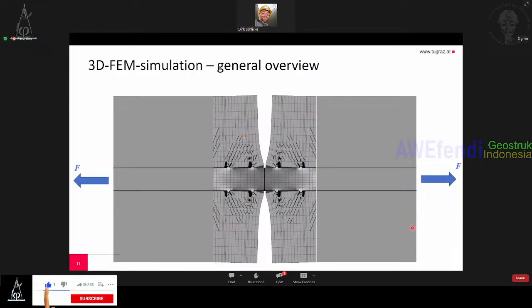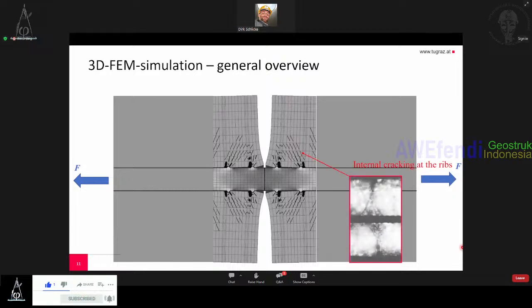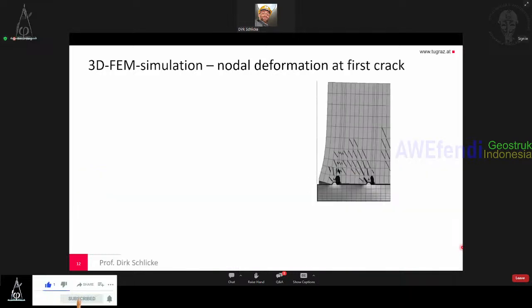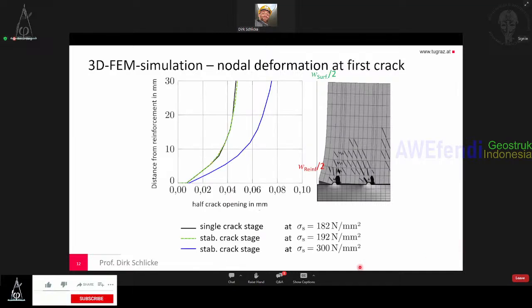This is how it looks like if you look a bit closer. And what you can see here is this internal cracking at the ribs is also represented by the fracture of the concrete. And we can also obtain the crack width at the reinforcement and also at the surface. Plotted in a diagram for the half system in length direction, you have the half crack opening in millimeters over the height. You see this distance from the reinforcement. It's very small crack width, and then the crack width increases, as we saw in the experiment from Broms and also from Ferguson.